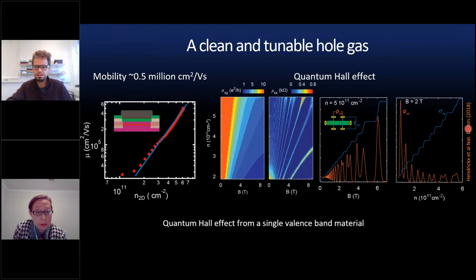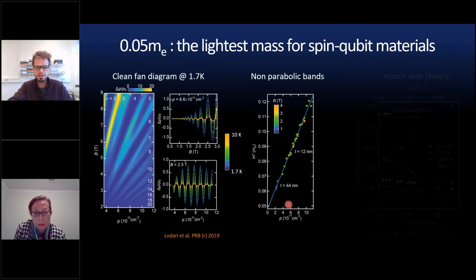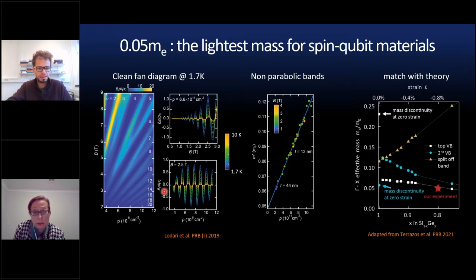You can measure all kinds of 2D physics. These are beautiful quantum Hall effects, like textbook. And here we can now really prove that we have a single valence band material from these measurements. We can also measure the effective mass of the system without going into details. The high quality allows us to measure the mass in transport. And you can see in this plot how the mass at small densities, meaning near the k equals zero part of the band structure, is really very light, 0.05 electron mass. And this is really the lightest mass ever measured for a material that hosts a spin qubit.